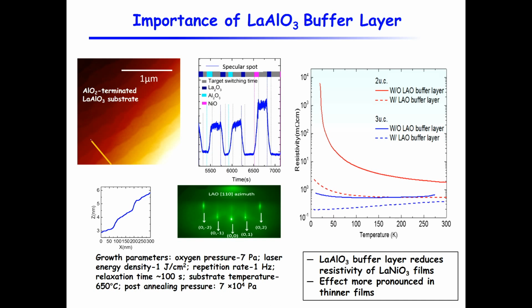Does that mean that the old target is still infusing for a while after you stop hitting it? Well, you can rotate it any time during this time, but the students purposely leave the sample there for some seconds. And we found that it's important. If you don't do that, you don't get samples as well.